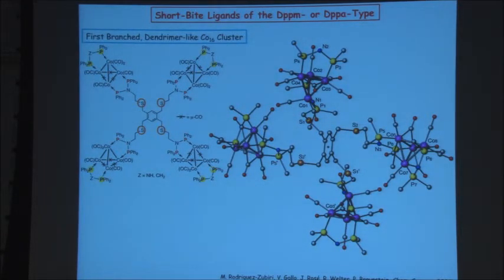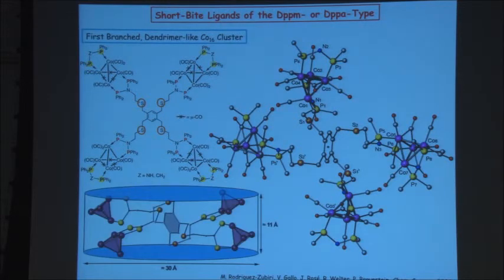By X-ray diffraction. Very tedious to grow the crystals. This system is very difficult to handle, but at least we could be sure that indeed we have this sort of a short bite ligand on the diphosphine functionalized here, assembling this nanocluster whose size is shown here, 30 angstrom by 11. Basically, once you have that on the surface, we should be able to observe them by various spectroscopic methods.